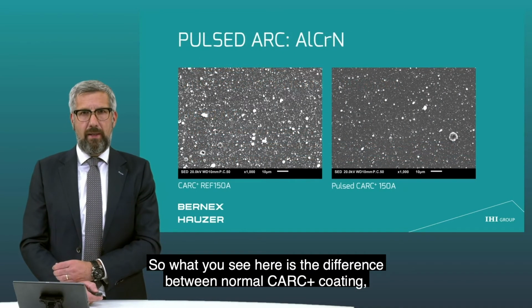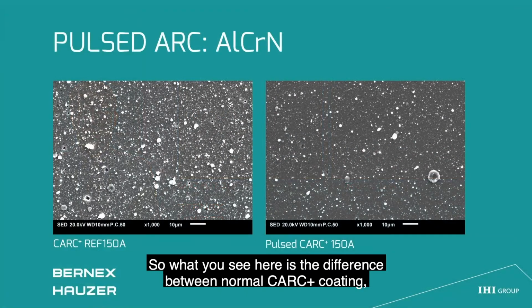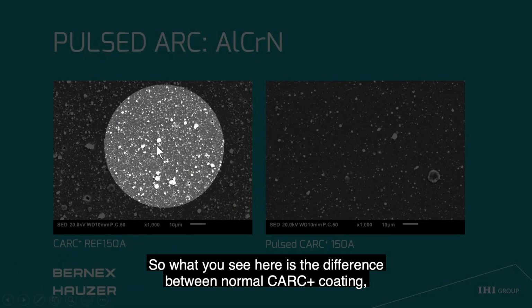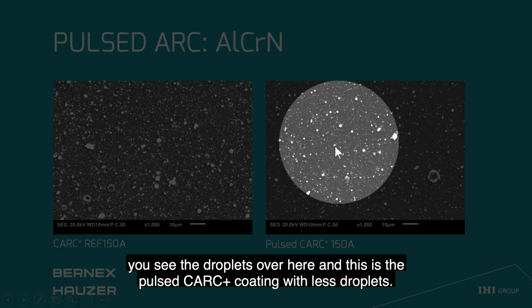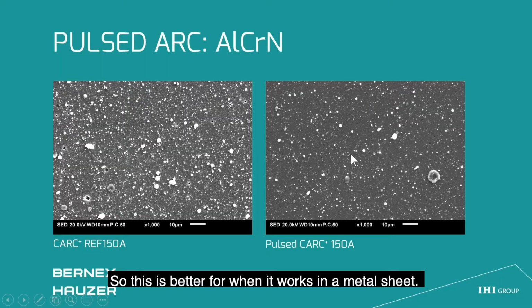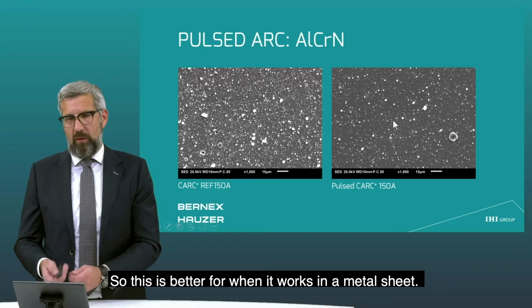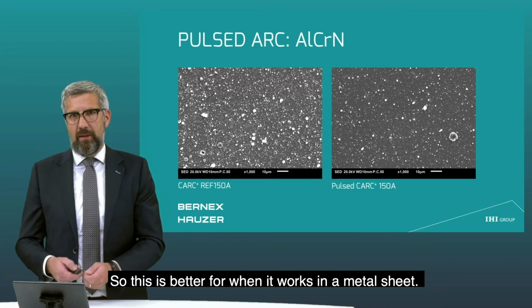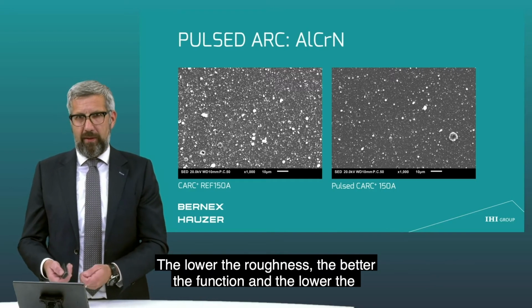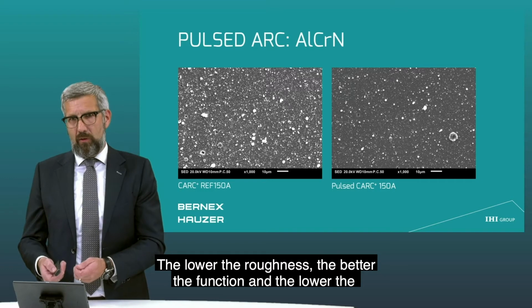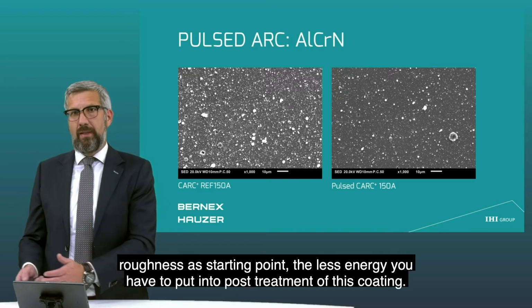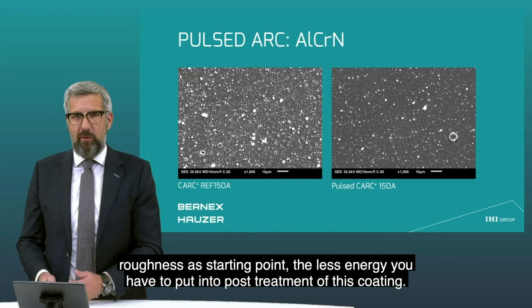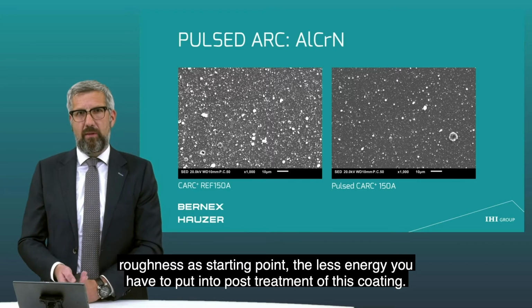So what you see here is the difference between normal CARC+ coating. So you see the droplets over here, and this is the one with the arc but pulsed, and you see much less droplets. So this is better for when it works in a metal sheet. So the lower the roughness, the better it functions, and the lower the roughness as starting point, the less energy you have to put into post-treatment of this coating.